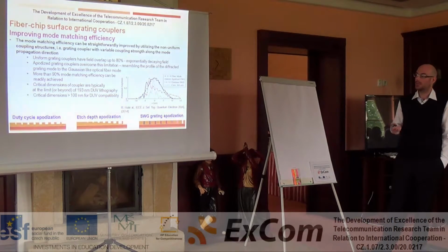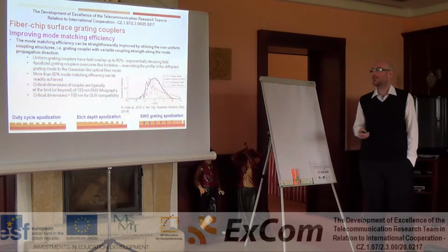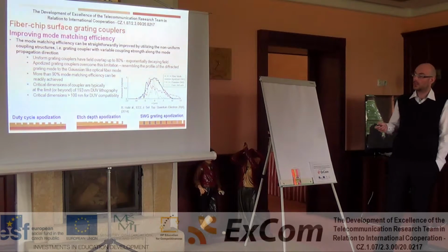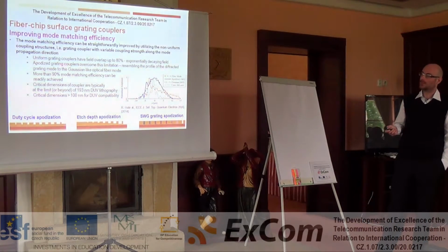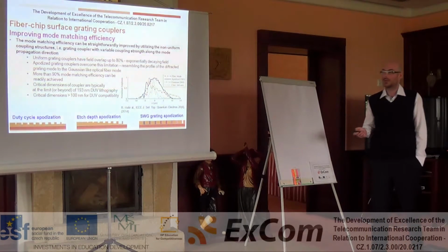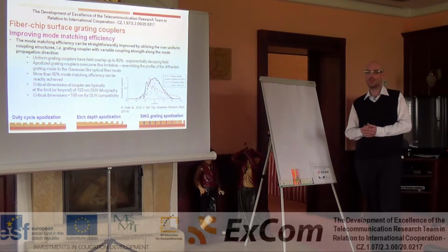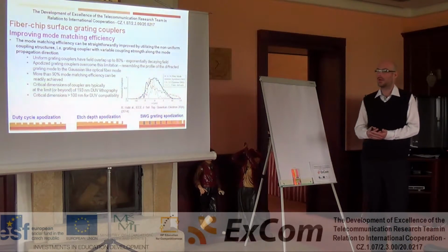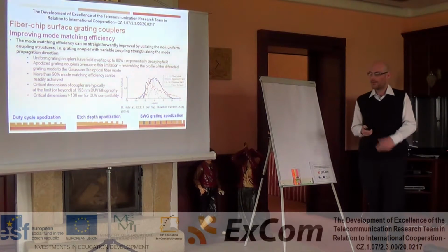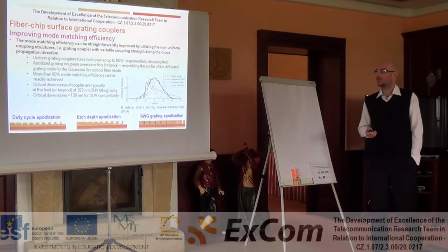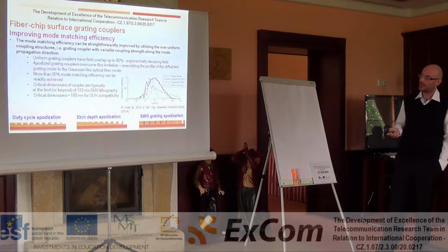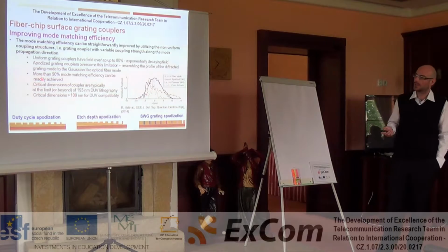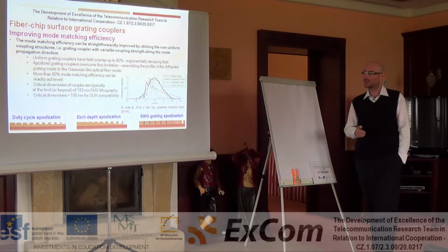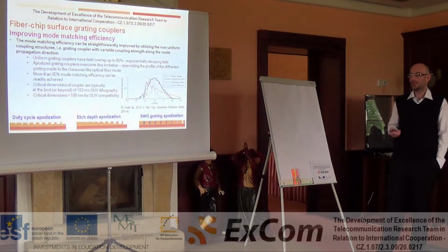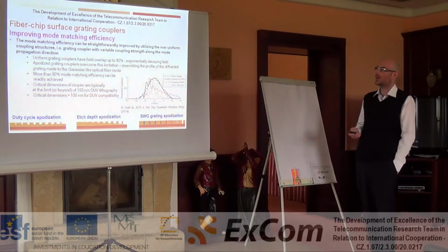Apodized grating couplers overcome this limitation. In this way, we resemble the profile of the diffracted grating mode and we match it to the Gaussian-like optical fiber mode. More than 90% mode matching efficiency can be readily achieved by simply changing the geometry of a grating coupler, and in this way we don't need to include some additional fabrication processes. However, in case of grating apodization, critical dimensions of grating coupler are typically at the limit or beyond the limit of DUV lithography. The critical dimension should be higher than 100 nanometer.